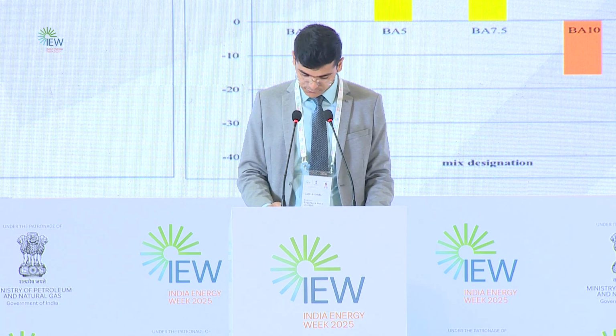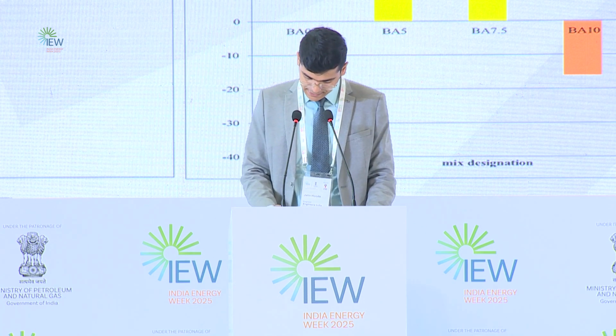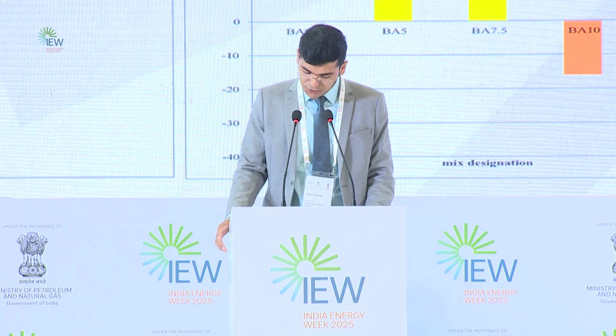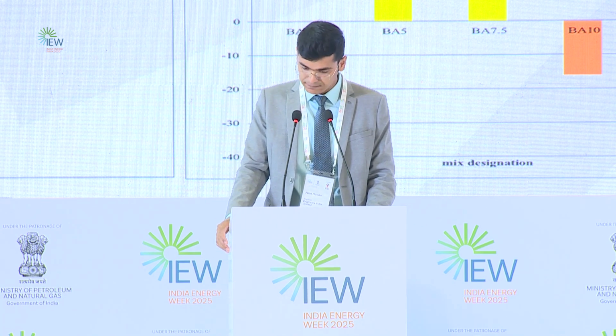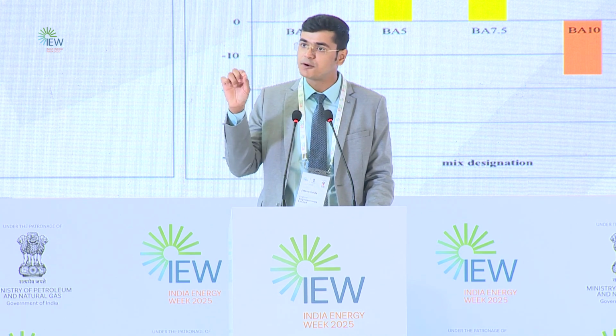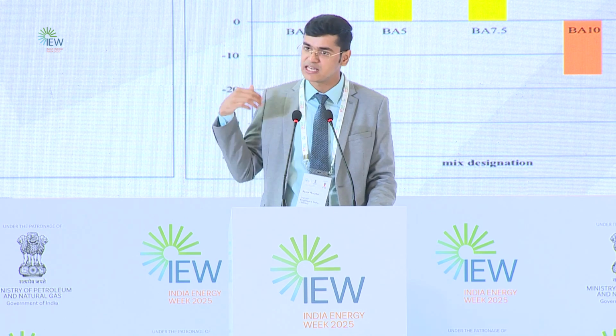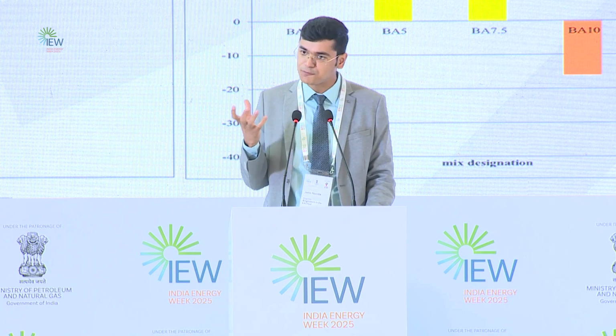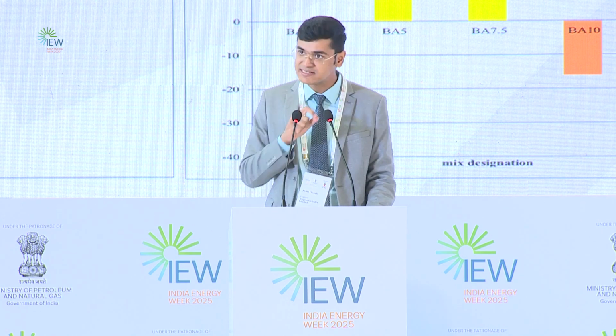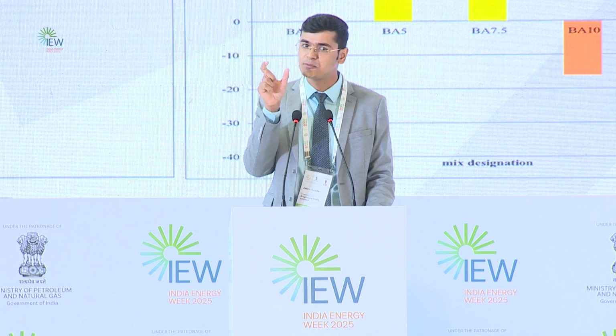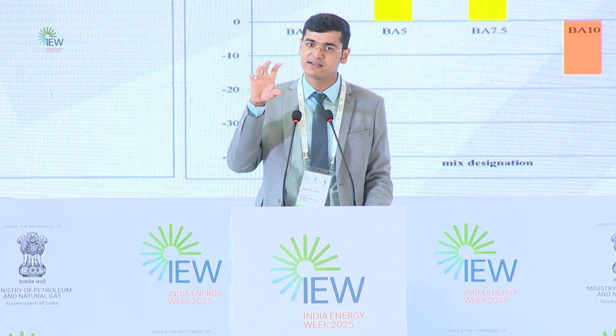Now talking about flexural strength, the same trend is seen for flexure also. At 7.5% we received a maximum. With the addition of a fibrous material like SCBA, which has long fibrous particles as I'll show from the EDS in upcoming slides, the concrete matrix gains tensile properties. It acts as a small reinforcement in concrete. That's why the flexural strength increases.